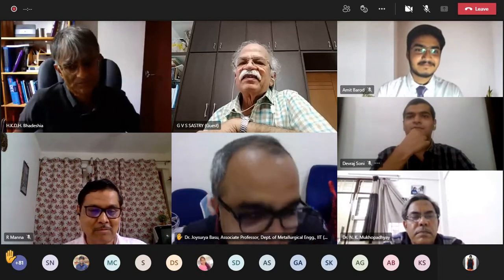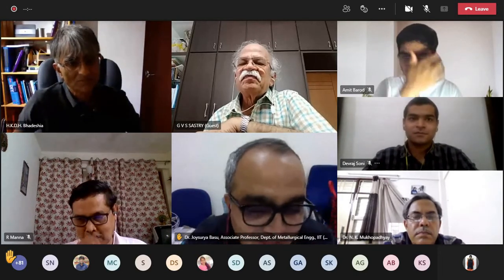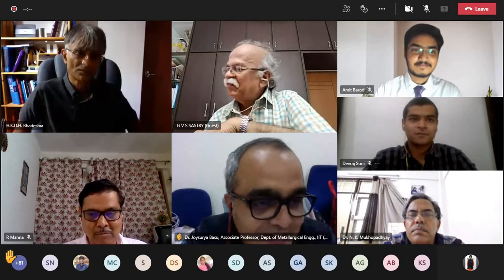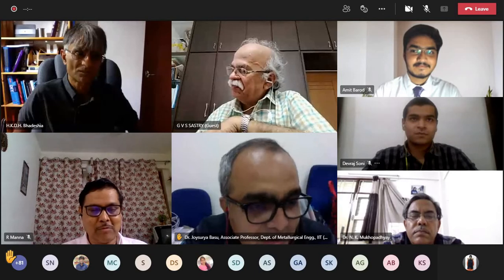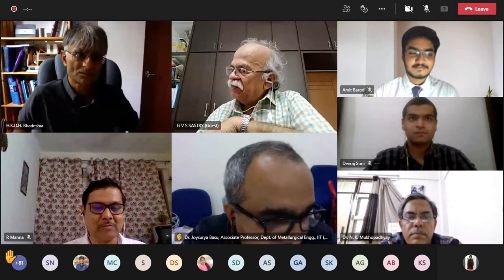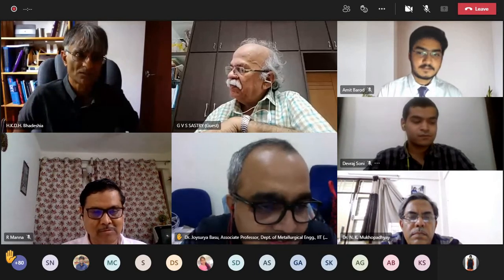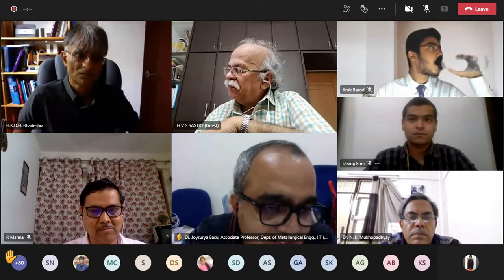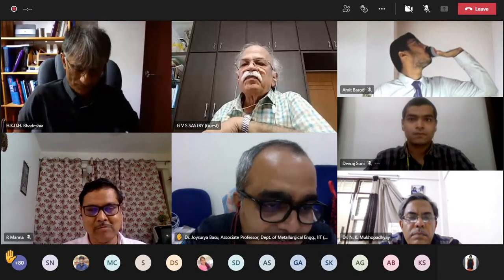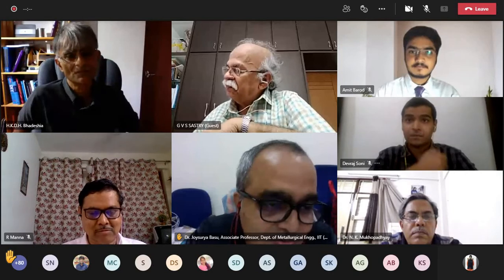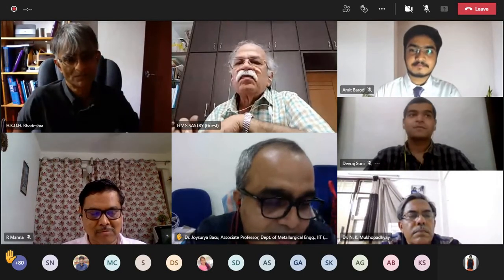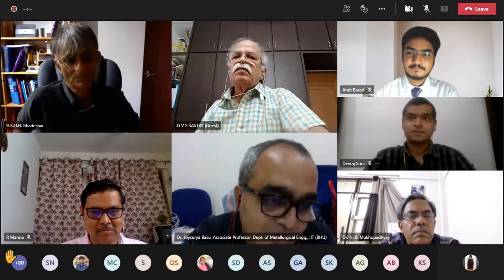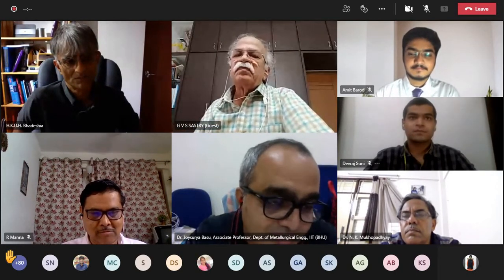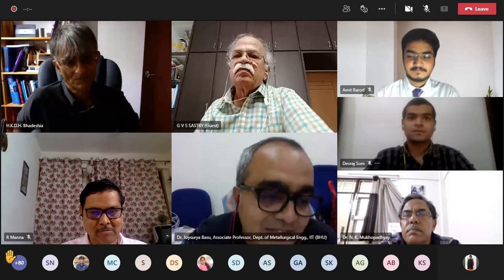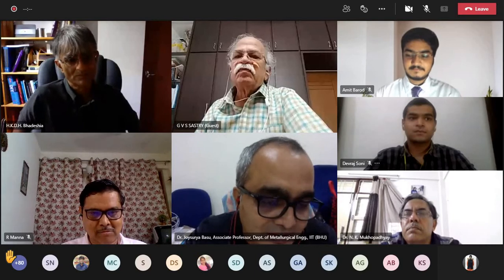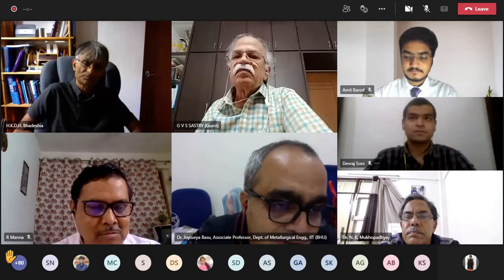Thank you. Actually, sir, this is a very nice, stimulating lecture. What I'd like to know is regarding the TWIP steel. So far I know that interpenetrating twins in steels were reported by Jack Christian and Basinski way back in 1958-60, but they never mentioned TWIP steels in those papers. And now we understand that these twins are mostly deformation twins, mostly compound type deformation twins. And by changing the deformation that you apply to the material, you can change the alignment of the twins also.